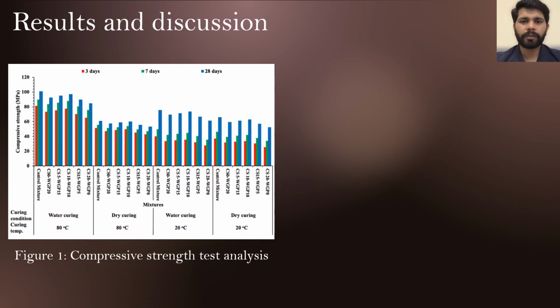Now we will talk about some results. Figure 1 explains the compressive strength analysis of all mixtures under both curing conditions and curing temperature. High temperature water curing showed the maximum strength in all curing types due to accelerated hydration that can be seen in figure 1. The control mix showed a compressive strength of 101 megapascal and incorporation of waste glass and Cenosphere apparently reduced the compressive strength.